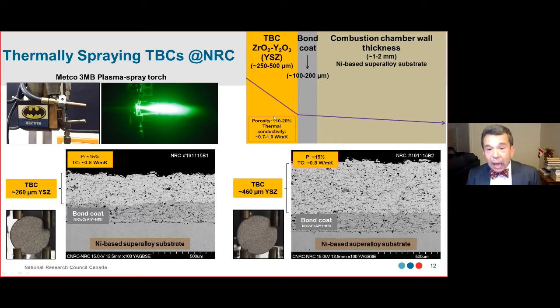And I have been telling you that the porosity of these TBCs is between 10 to 20%. And the porosity of our TBC is 15%, so we are inside the limit. I have also been telling you that the thermal conductivity of these TBCs is between 0.7 to 1 watt per meter per Kelvin, and the thermal conductivity of this TBC is 0.8. So we're right at the good point of having a representative TBC.